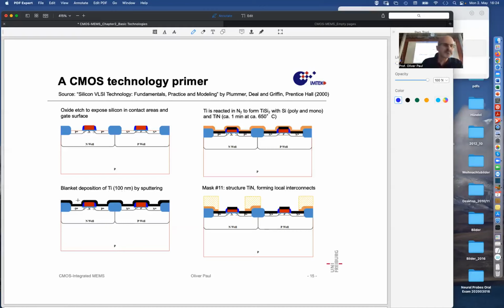So this sputtering is different from evaporation deposition. There are two physical deposition methods. One is called sputtering and the other one is evaporation deposition. In evaporation deposition, a target is usually heated by an electron beam to a high temperature, or resistively, and then metal atoms just escape from some hole and then project linearly onto the substrate where they get stuck. So that's a directional process.